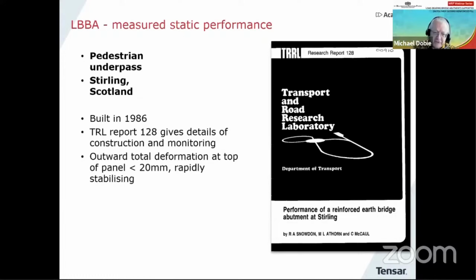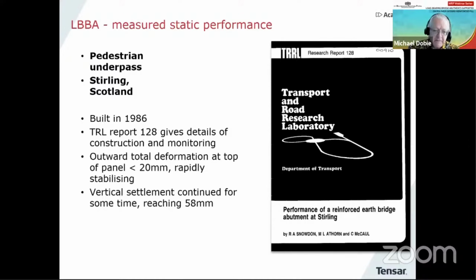it was found that the total deformation at the top of the panel was less than 20 millimeters, and it rapidly stabilized. If you want to see this in more detail, you'll have to get hold of that report or ask me for a copy of it, but you'll find a lot of information in there. The vertical settlement actually was bigger than the horizontal movement, but because of the slightly compressible subsoils, they got up to about 58 millimeters of vertical settlement, which also reduced with time.